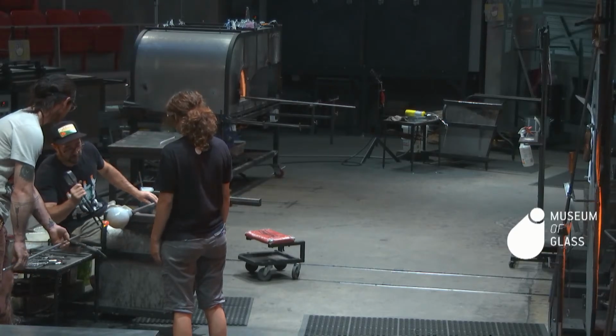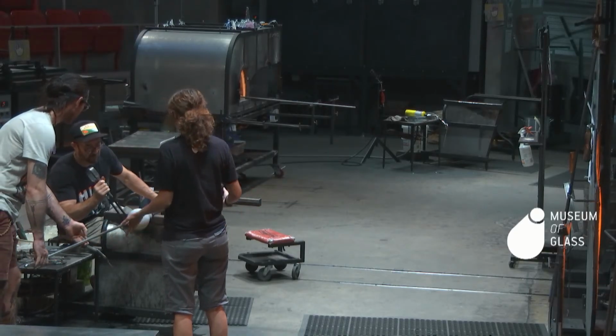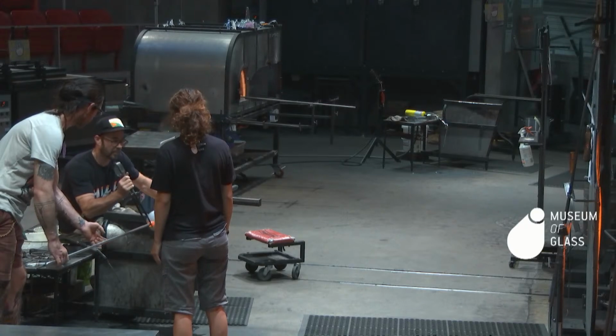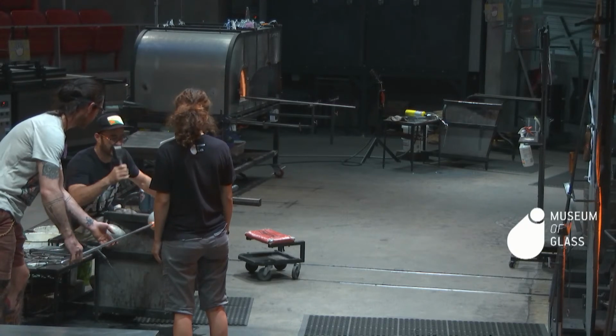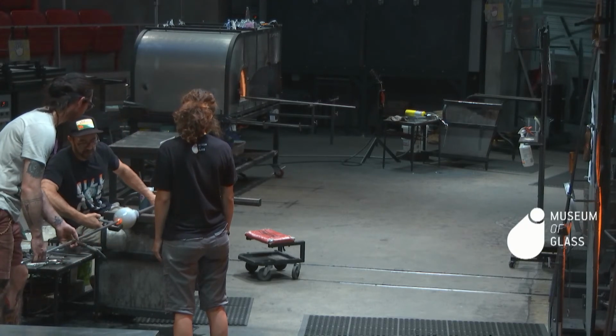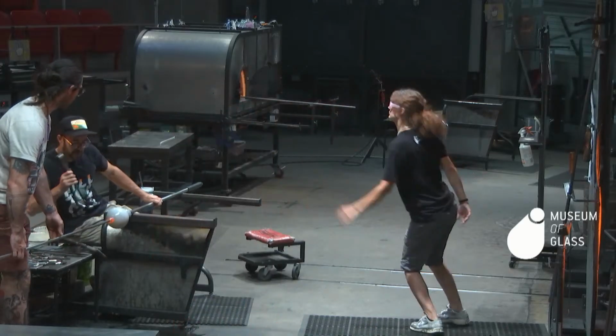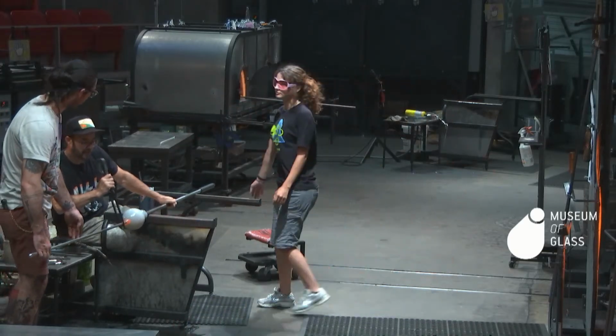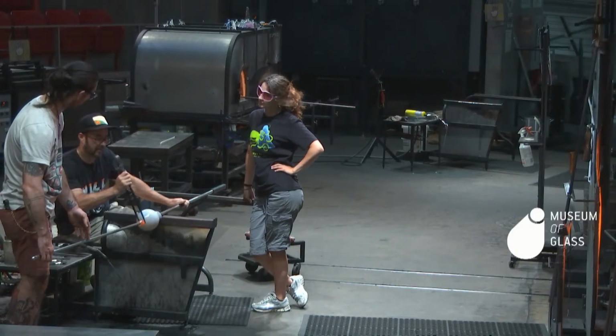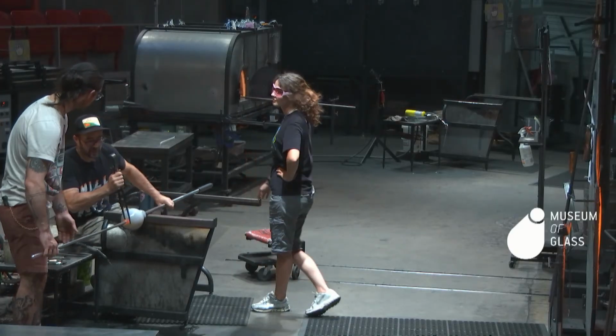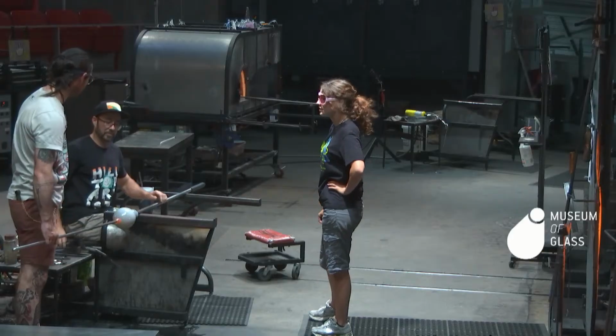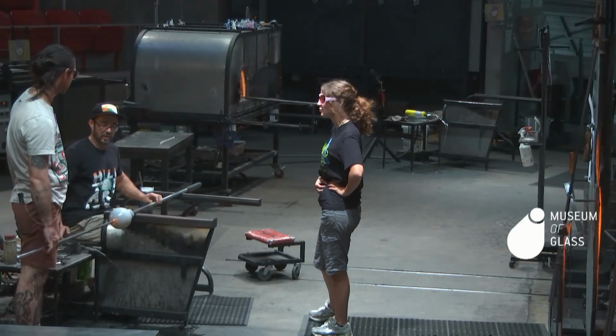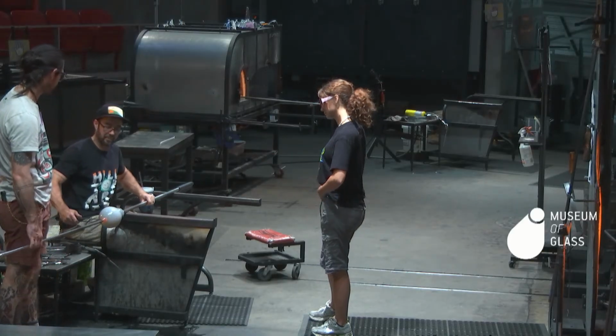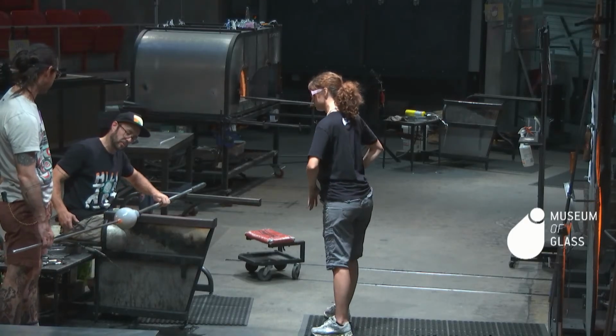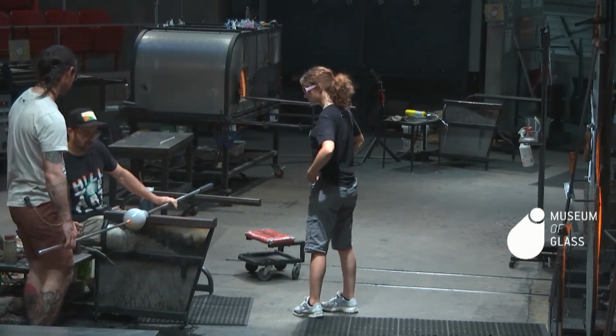Hot glass sticks to other hot glass. So at the right temperature, these can get stuck together. And then just like they got the bubble off the other pipe, you're going to do the same thing with this one. At the right temperature, you can put water on that restriction line, and it will shock the glass, creating little cracks, essentially making a weak spot. You hit the pipe with a metal tool, and it sends those vibrations through the pipe and into the weak spot, and it breaks it, separates it from the pipe.